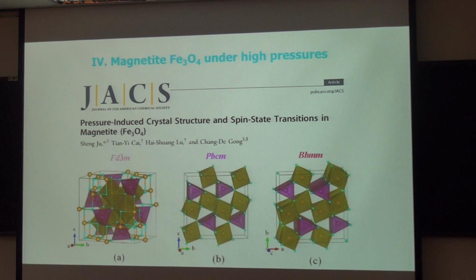What we have done is we studied the high pressure physics of this magnetite. As we know, magnetite is the oldest known magnetic material in human history. And there's no doubt that at ambient pressure and room temperature, it crystallizes in this inverse spinel crystal structure. In fact, this crystal structure can be determined exactly. For the high pressure phase, experiments have identified two kinds of symmetry, the Pbcm and the Bbmm.